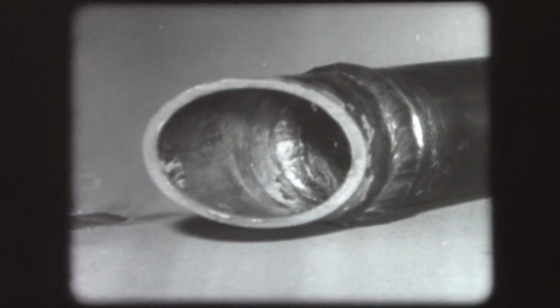Notice how even this weld is, with a uniform width and height. This indicates that the weld was properly made and is the result of using a constant welding speed and maintaining a continuous rod flow. The inside of the tubing also shows a good weld. There is no excess penetration and no metal drip.